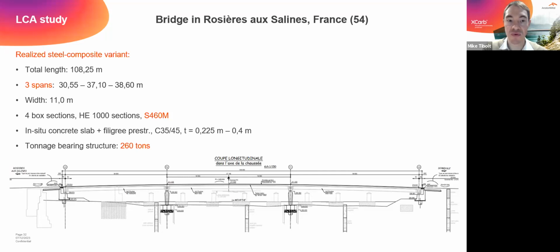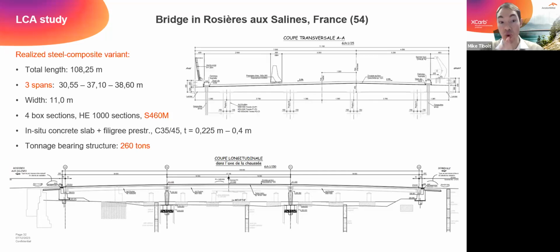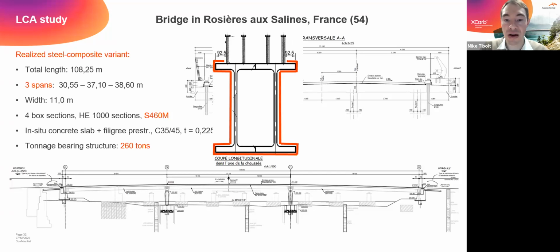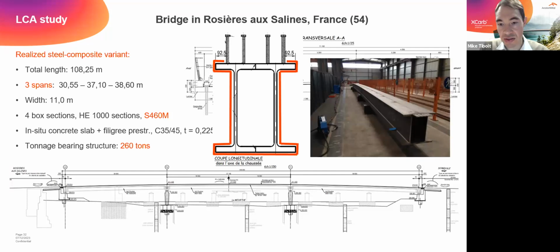That is high-strength steel for hot rolled sections, because by switching to high-strength steel, you can reduce the section size and save additional material and also the weight of your bridge. It was done as a combination with in situ concrete slab, which was cast on filigree pre-stressed concrete in C35/45, and the tonnage of the steel structure was only 260 tons. So by using this high-strength steel, and here you can see how we welded the hot rolled sections at the level of the flanges together to form this box section.